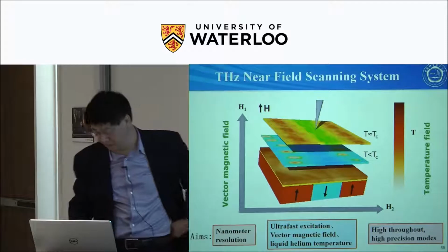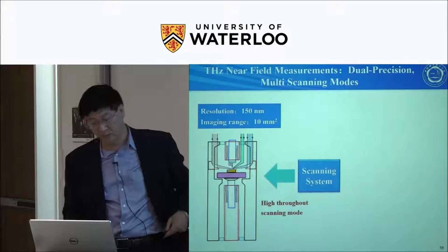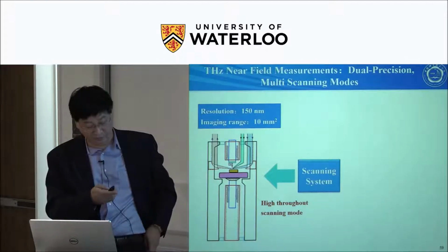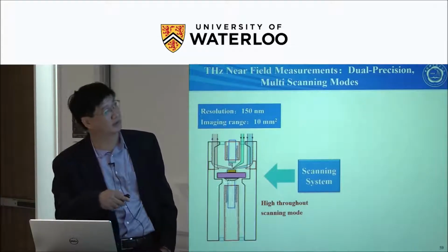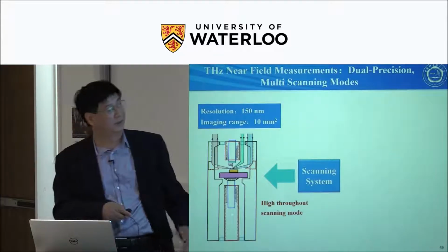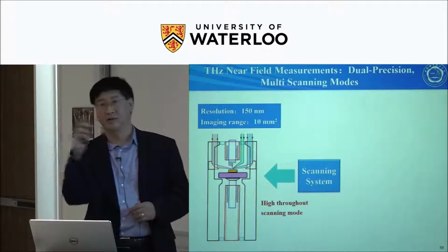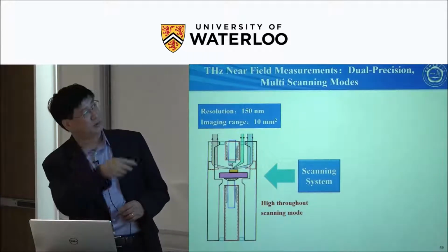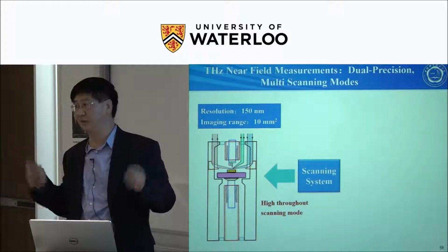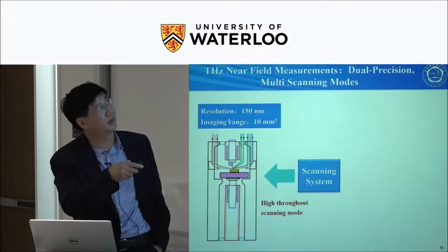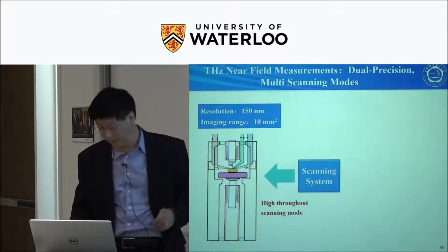So that is the system we are working on right now. What we succeeded in is that we first developed this large-range, high-throughput scanning mode. We use piezoelectric actuators to step through, so we can go all the way to 1 centimeter in distance. The spatial resolution we can realize is 150 nanometers. This is in high-throughput operating mode.